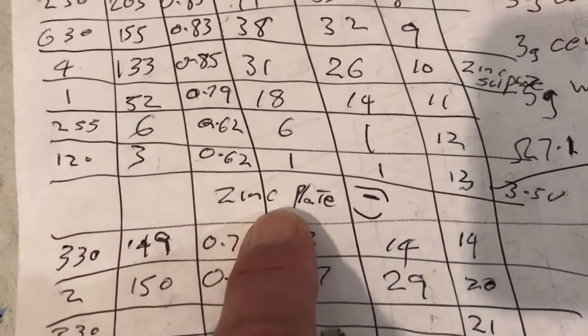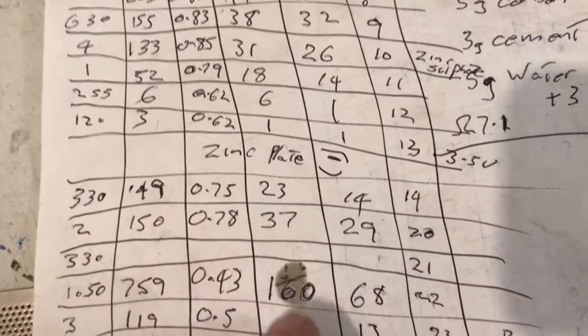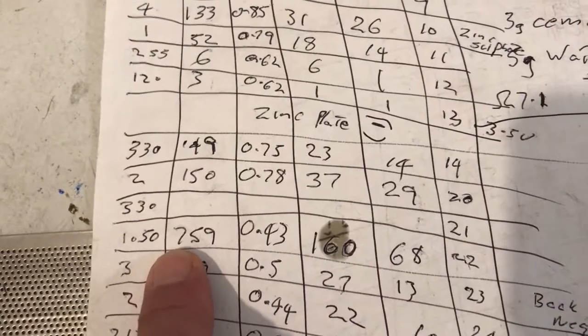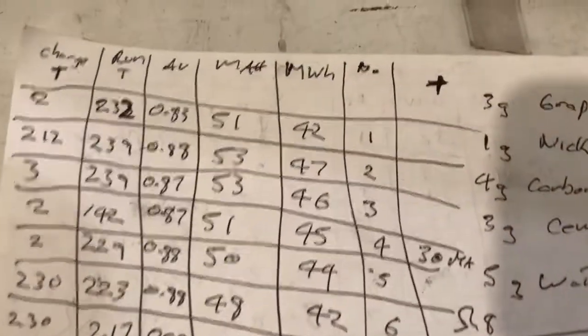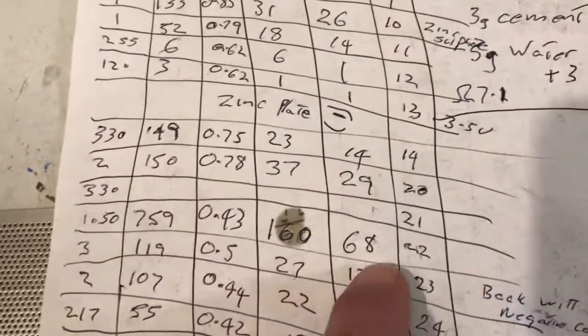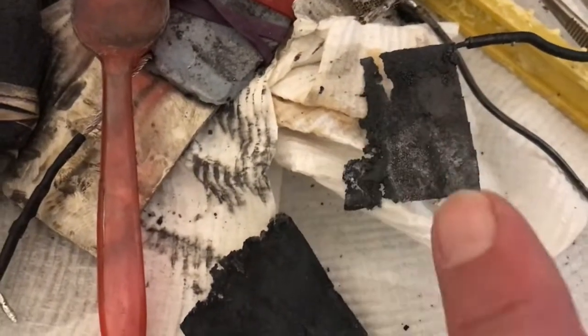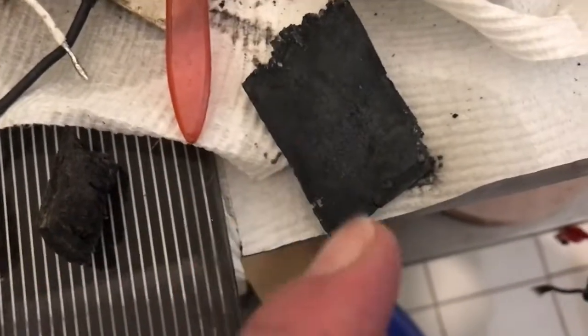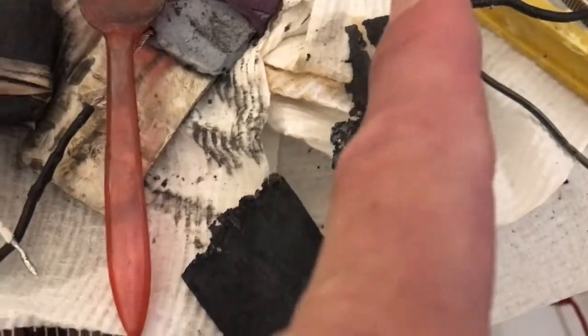And I've substituted the negative plate for a zinc plate. Slight improvements. I ran this one to 0.2 of a volt, went for 7 hours and 59 minutes with 68 milliwatt hours and 160 milliamp hours. But if you do that and run it down to 0.2 volts, your zinc plate will end up like this. It played out on a charge, but it decided to consume it near the top of the electrolyte. And I reckon you can see the zinc floating on the top there.